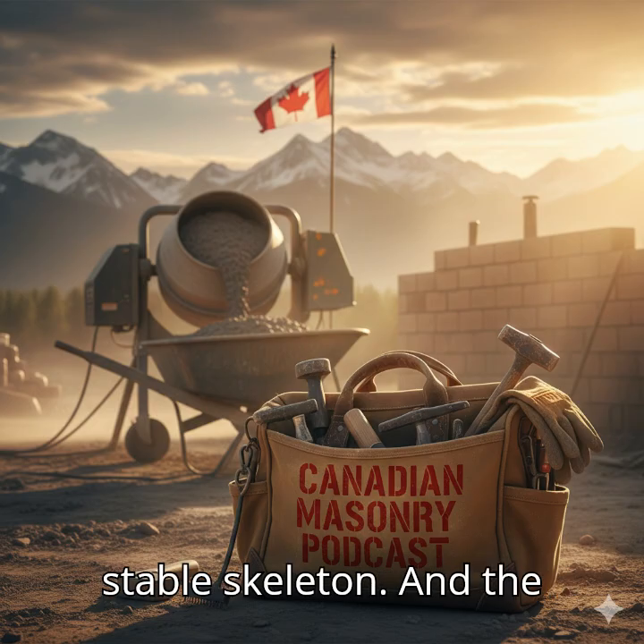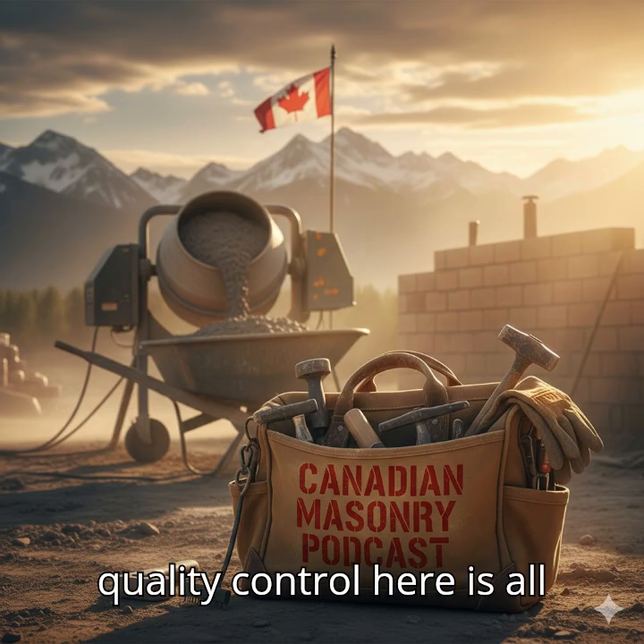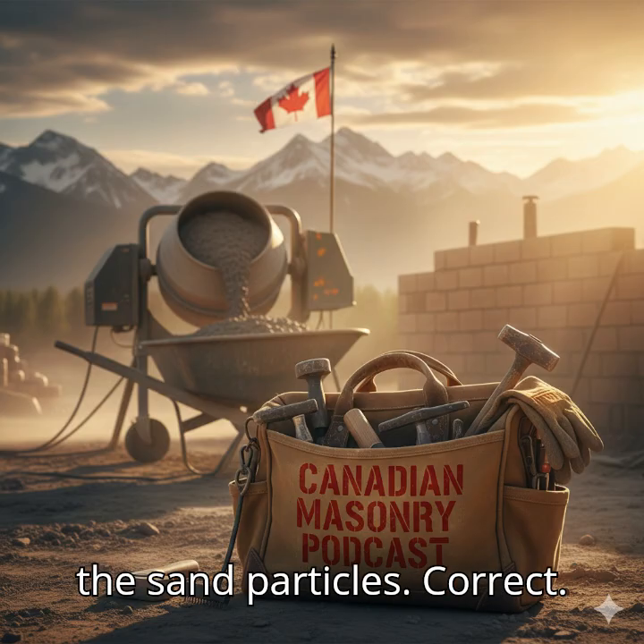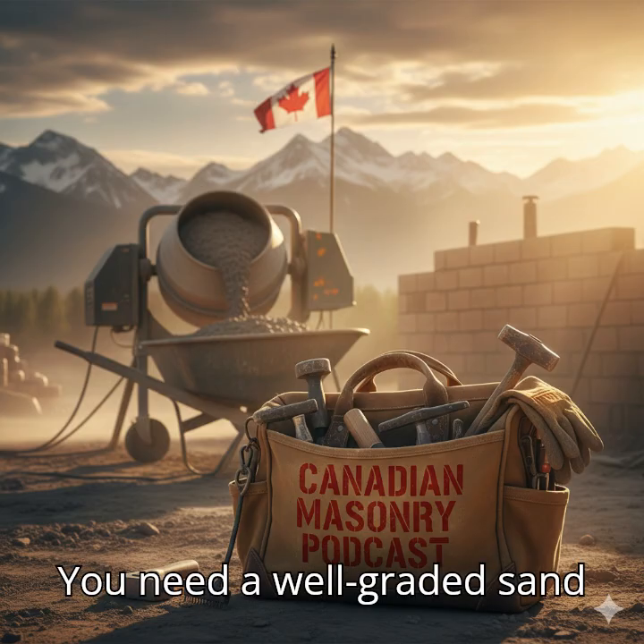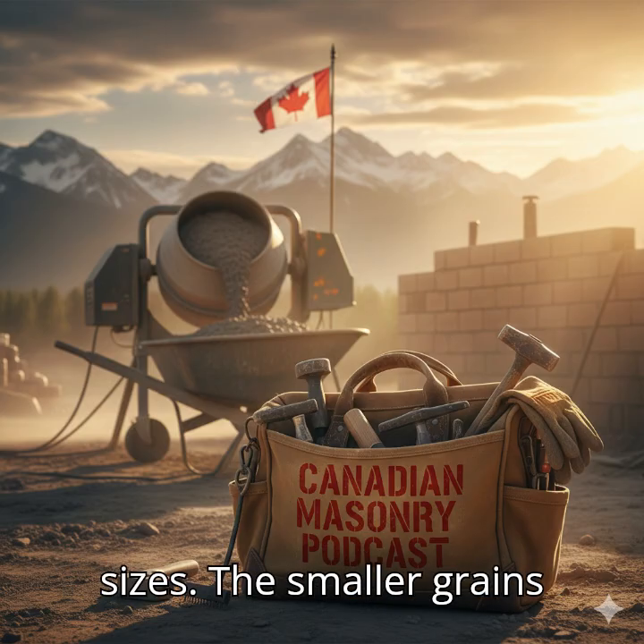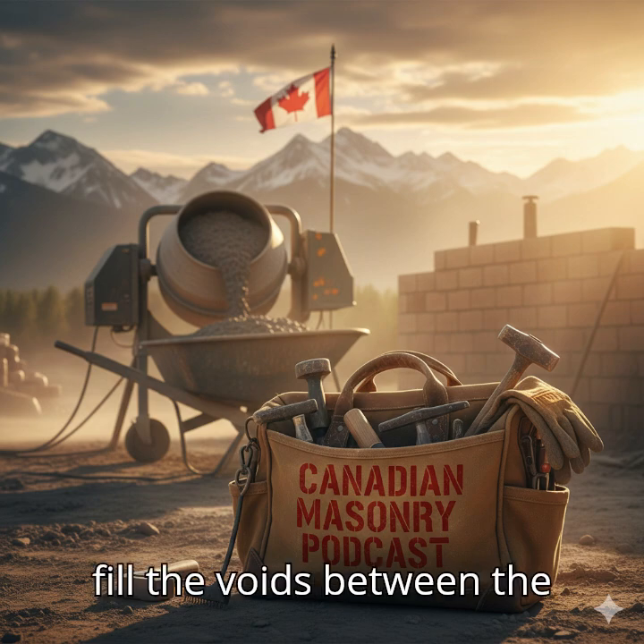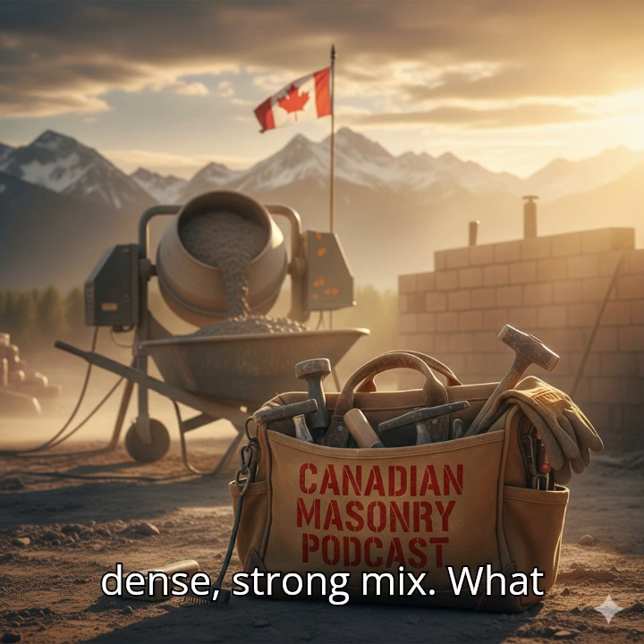Sand provides the stable skeleton. And the quality control here is all about gradation, the size of the sand particles. Correct. You need a well-graded sand with a good mix of particle sizes. The smaller grains fill the voids between the larger ones. This gives you a dense, strong mix.